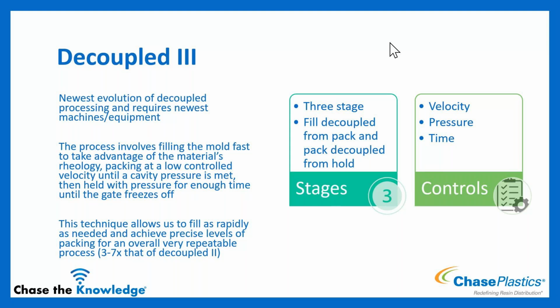Now you may ask, when would that be extremely critical? High volume multi-cavitation tools can benefit greatly from a decoupled three process, but so can insert molds, especially if the inserts are delicate and have a maximum pressure that they can tolerate during the molding process without being damaged. So you may see magnets inserted using a decoupled three process to protect the magnet. If you have any sort of chip or any sort of instrumentation that you're going to be overmolding, those inserts can only take so much pressure. And if we were to go under a traditional decoupled two, we might overpressurize the cavity and start running into rejections due to destroyed inserts. So the decoupled three process then gives us full control of the amount of pressure in the cavity during the packing and holding phase.